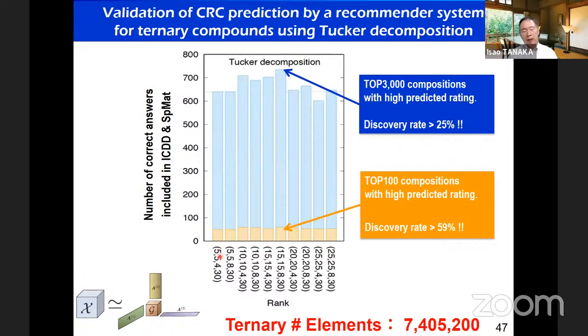And this is a result. This axis corresponds to the length of the core tensor, and you can see that the result is almost independent of the length of the core tensor. And this vertical axis corresponds to the number of correct answers included in a test set, which is ICDD or Springer Materials data set. The height of these bars corresponds to the success rate within the top 100 compositions with high predicted rating. Among these 100 compositions with high predicted rating, we found that 59%, or 60, already exist in the test set. The success rate was found to be close to 60%.